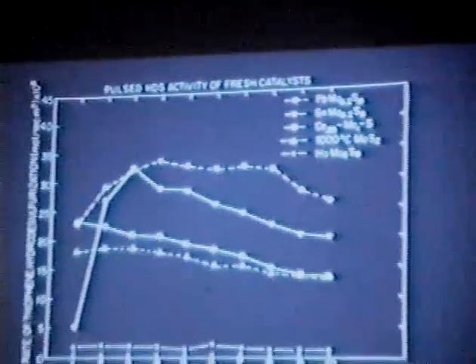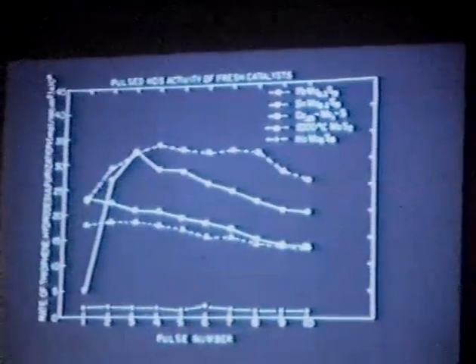Some other compounds, we really don't understand what happens with some of these. For example, the tin Chevrel phase compound also undergoes a kind of activation here. Even the lead Chevrel phase does too. There doesn't seem to be much motion of the ternary metals for these types of compounds. What I should point out is a little bit of studies with benzothiophene, and again, I regret that I don't really have too much to say during this talk about this, but the activities here for this lead Chevrel phase compound aren't too far off from what the conventional cobalt-promoted molybdenum sulfide compound looks like.